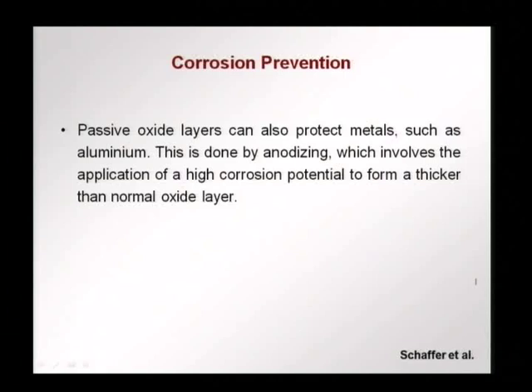Passive oxide layers can also protect. Remember, when we talked about oxide layers, we said that some oxide layers do not have much volume change. They stick to the surface of the metal and will not allow oxygen to go through or the metal to diffuse out. This can be enhanced further by a process called anodizing, where we purposefully increase the thickness of the oxide layer. Anodizing involves the application of a high corrosion potential, giving rise to a thicker than normal oxide layer, and this oxide layer now protects the anodized metal from further corrosion in application. So, this becomes part of the processing itself. We purposely increase the oxide layer by anodizing, and this prevents further corrosion from occurring.